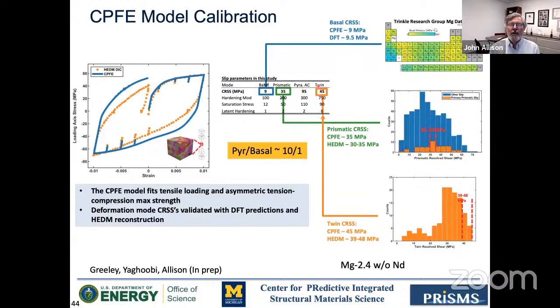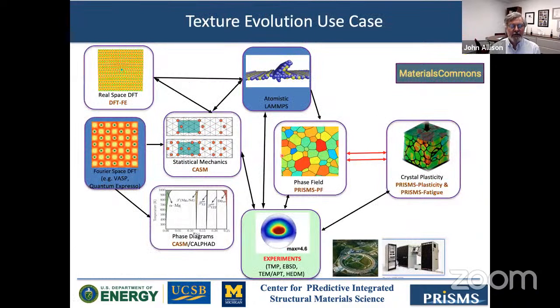And twinning has gone to 45. So importantly here, now we're seeing a fairly substantial increase in twin critical resolved shear stress due to neodymium, even though we have a low number, so that's difficult to quantify, but we feel that's a pretty reasonable estimation. But also importantly, we see pyramidal to basal ratio is 10:1. So again, this is part and parcel of why these alloys have a lower texture. Okay, and this is something that will be getting out soon. We have a manuscript in progress on this.